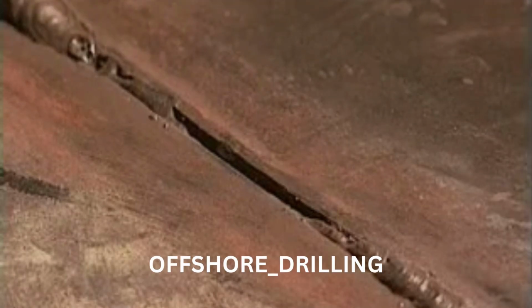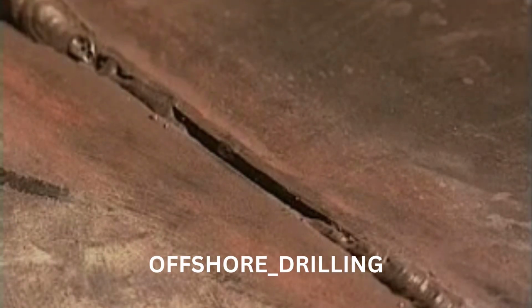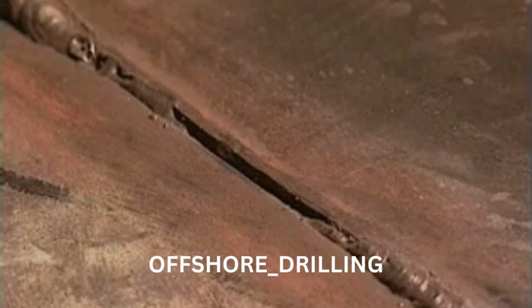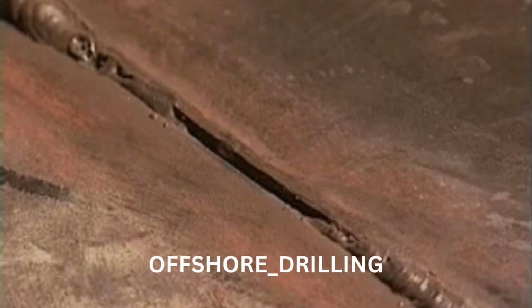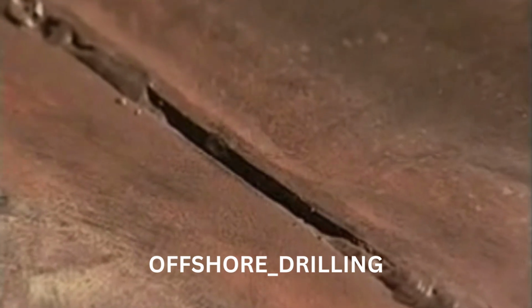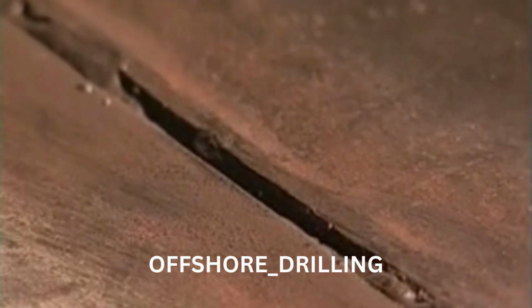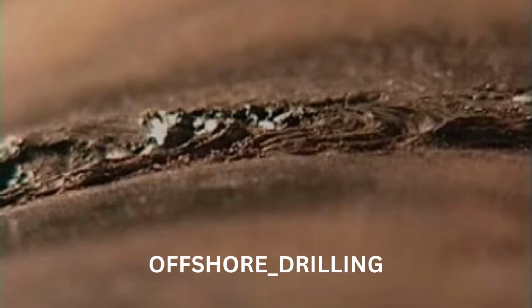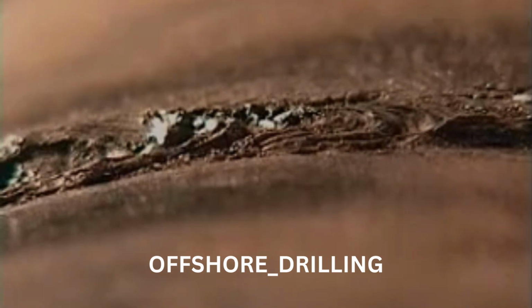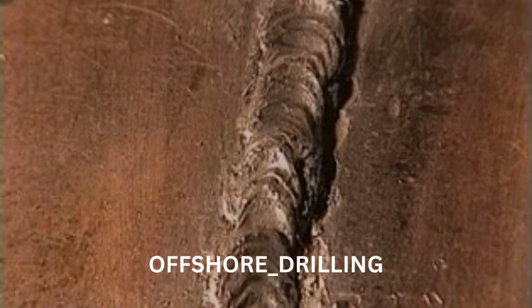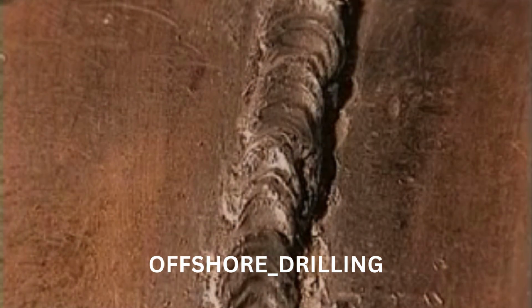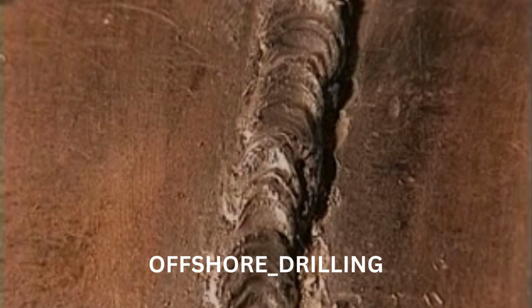Also, moving the filler rod or electrode too rapidly can result in incomplete penetration, where not enough material is deposited to reach the base of the joint. Undercutting, or valleys, where the center of the weld bead is lower than the sides, are another symptom of too high a travel speed. Either of these faults can cause cracks to appear in the weld.